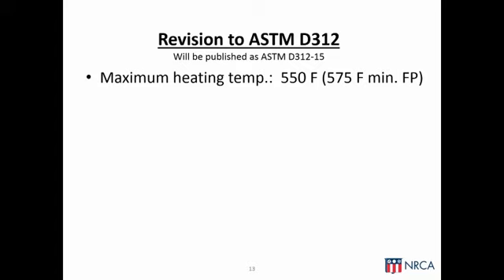And then that corresponds to a minimum flash point for the asphalt of 575. And that is a relatively significant change from the previous edition of the standard that had a flash point minimum of 500. So in a sense, the standard is permitting a higher flash point, which may be construed as being counterproductive, but actually what we're doing is providing a maximum heating temperature, kettle temperature, or tanker temperature, that is probably notably lower than what is currently listed or what we're currently seeing in the field.